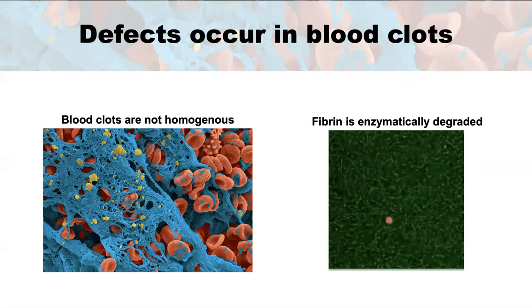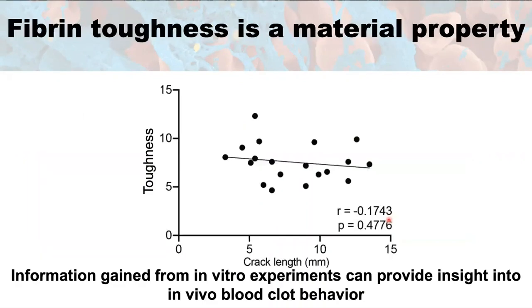So it is very important to understand how blood clots are going to behave in the presence of defects using these fracture mechanic techniques. So importantly, our findings show that the fracture toughness is in fact a material property. And so we were able to do this by taking those same samples that I showed in the video earlier and having crack lengths that varied in their length, or the fraction of the width of the sample.